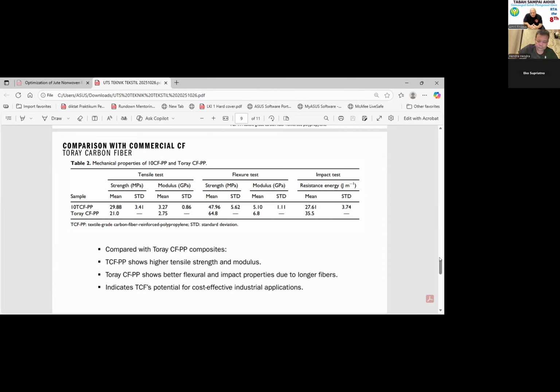Even so, the TCF-PP composite demonstrates excellent potential, especially considering its cost advantage. Producing TCF is significantly cheaper, and with further process optimization, like improving fiber length retention or using the side feeder technique, the gap could become even smaller compared to the original carbon fiber, or Toray carbon fiber in this case. So overall, this comparison reinforces the main message that textile grade carbon fiber can deliver comparable, as you see in the result, and in some cases even superior performance at a fraction of the cost, making it very promising for high volume industrial application.